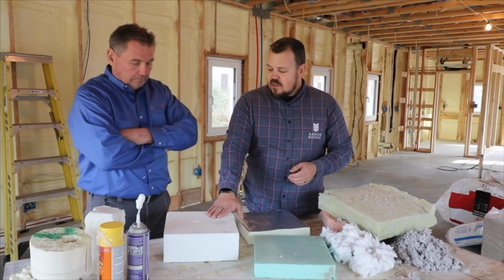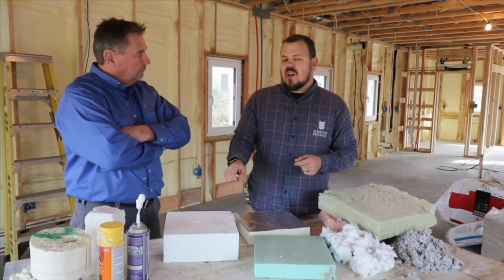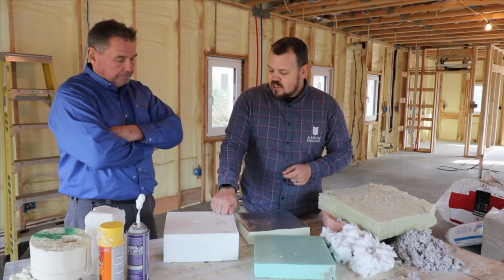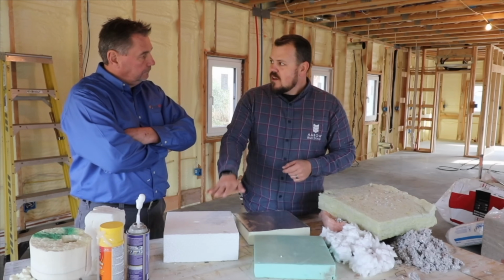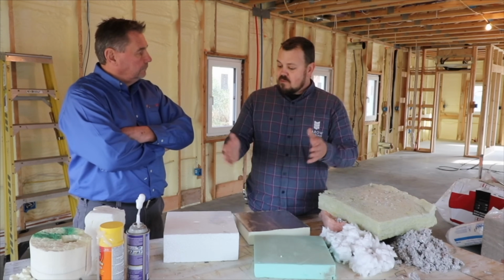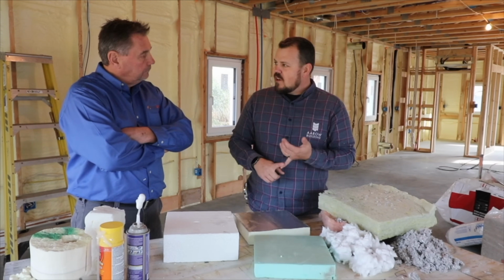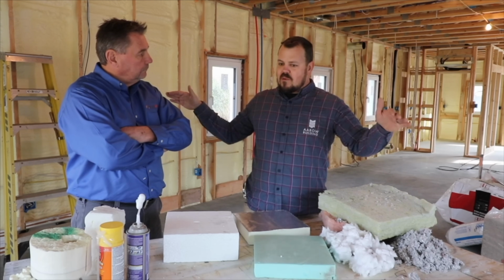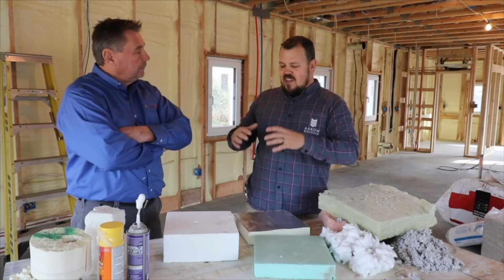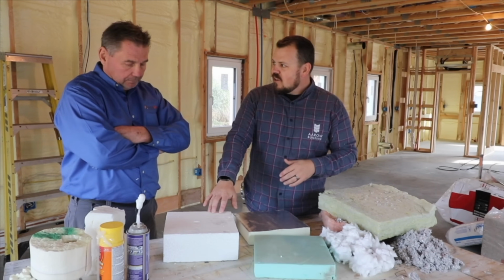We've used the EPS, and the EPS is an interesting conversation because you say it dimples, but at the same time we can order different kinds of EPS that have different compaction rates. Densities. Yeah, so this is actually a type 9. It's a 20 psi, which, if you extrapolate that out, is more weight than any house is going to have on it per square foot. The Type 9 specifically is what they put under heated runways. And if you've ever seen them building up on-ramps to build a ramp across a highway, that's what they use as backfill. Because they can get a lot of space with high compression quickly, cover it with dirt. They know this isn't going to biodegrade being underground.